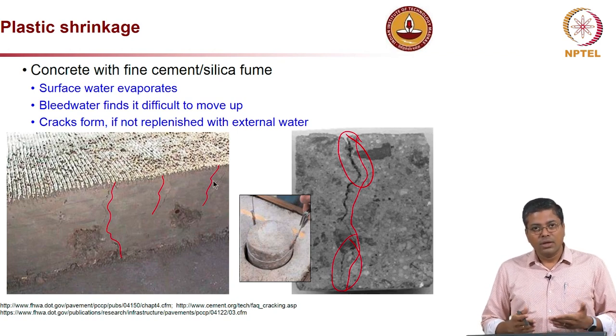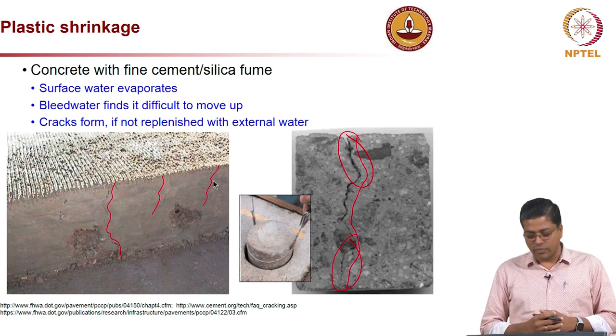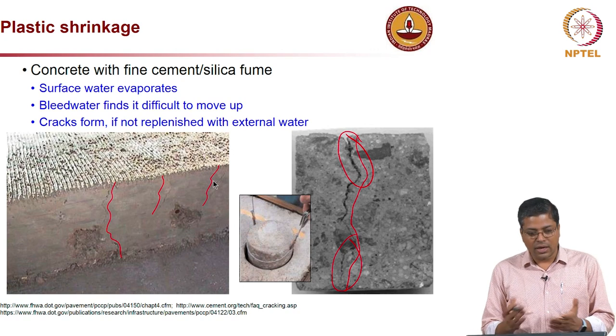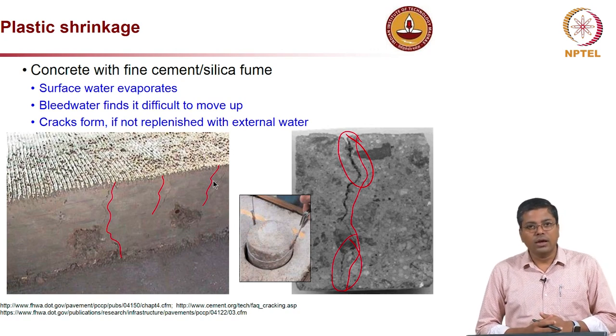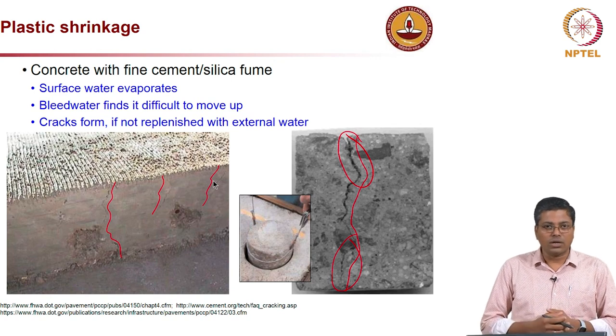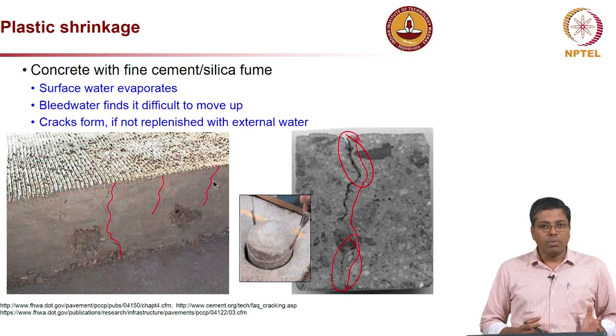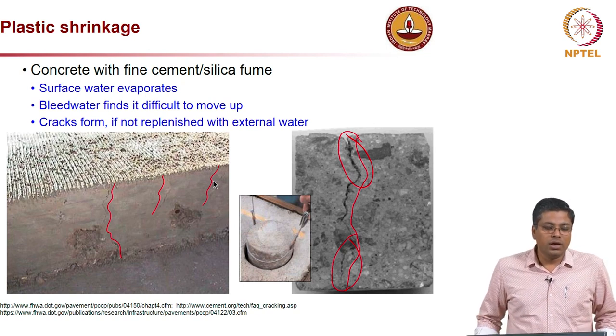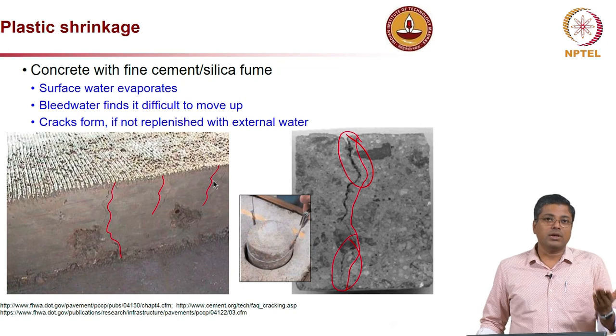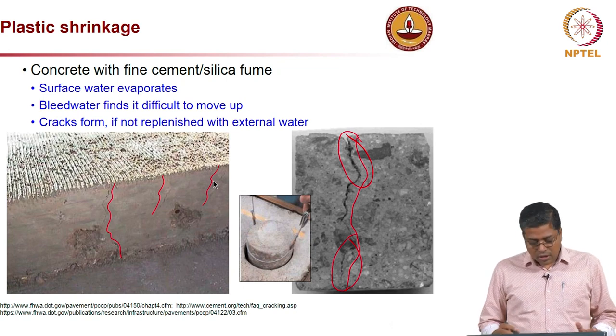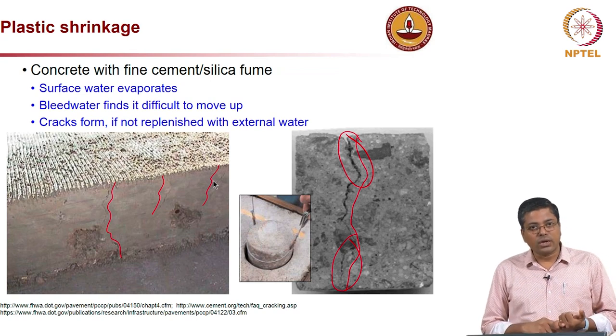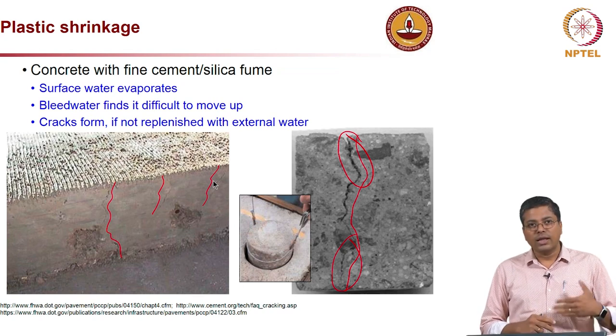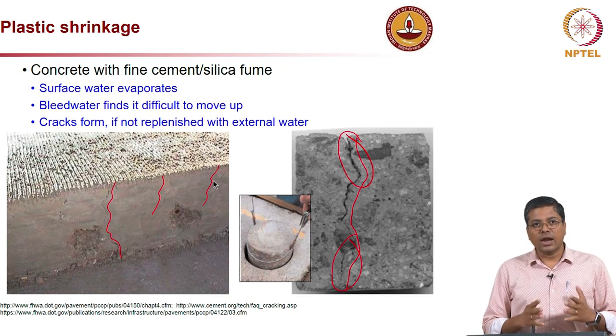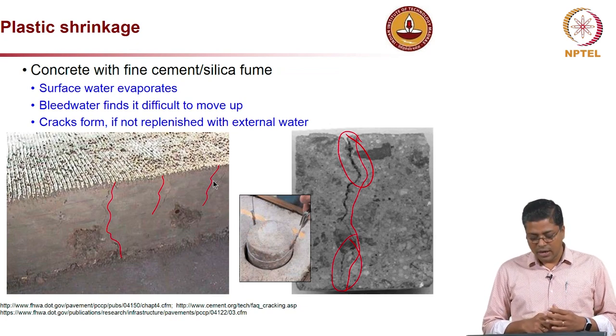And at the same time, if there is sufficient wind, or the surface of the concrete is relatively dry, the ambient air is a dry environment, then you will have evaporation or loss of water from the top surface of the concrete, but that does not get replenished with the bleed water, which is prevented from coming up. So, multiple actions. One is the surface water evaporates, and at the same time bleed water finds it difficult to move upward, and this condition leads to the formation of cracking, especially when you do not have enough water available at the top surface.